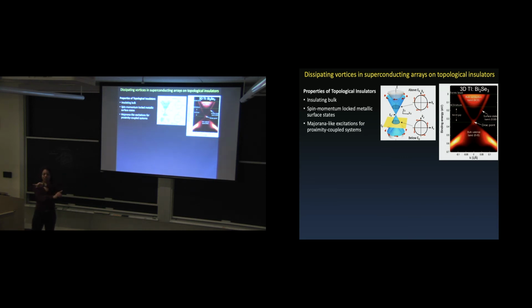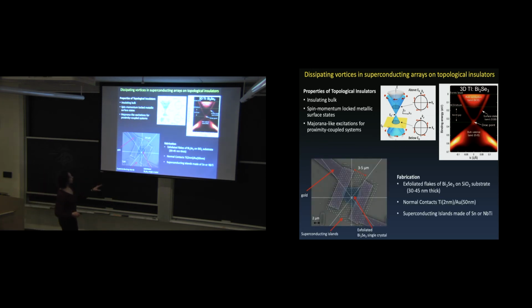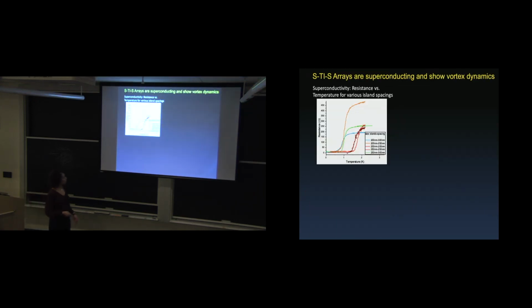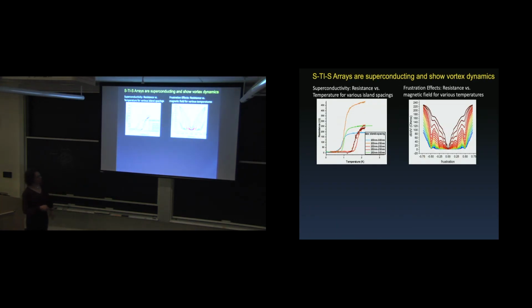Okay, so this might be interesting to look at vortex dynamics. You can imagine putting a vortex through, which forces your spin to go in one way, and then how does that affect how the vortices depin? So we end up putting these islands on a flake of bismuth selenide. Here's the bismuth selenide. Here's what we put on here. There we go, niobium titanium islands, mostly on there. And you can see we get all these same behaviors for the topological material.